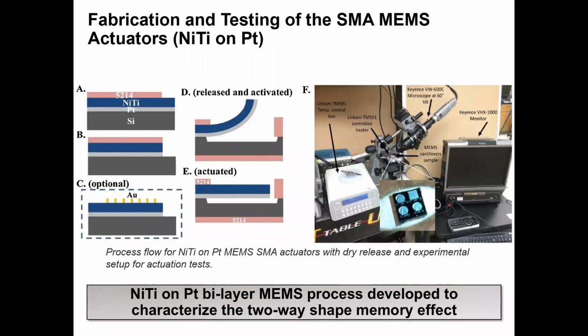So the SMA MEMS actuators suitable for actuation based on these previous measurements were explored using the identified processing conditions in the earlier contributions. So the processing figure on the left-hand side here, I started with NiTi and sputtered it directly onto a platinum-coated silicon wafer. Ion mill etching was then used to pattern the NiTi platinum bimorph using standard photoresist and mask plates. Device release etch was done using xenon difluoride, which selectively etched the silicon wafer, but doesn't affect the NiTi and platinum. So residual stresses caused the bimorph to curl up after the device release.